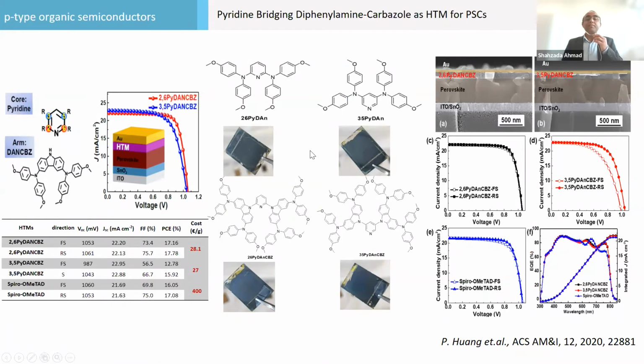Just with pyridine with HTM, the films were not uniform. If we put a carbazole, we were able to form a uniform film, which is very good for the interface and charge extraction. And we have a performance equal to spiro, and even higher than spiro, which gives 17 here. All these 2-6 positions give you higher.